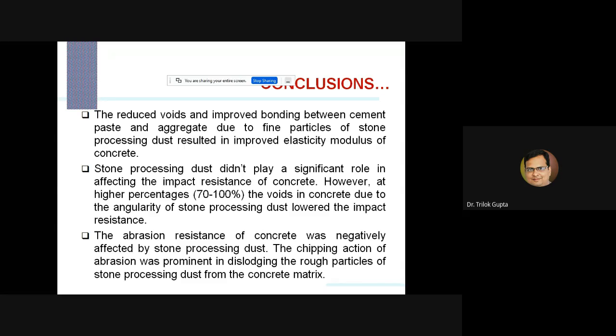However, at a higher percentage, meaning greater than 70%, the voids in concrete due to the angularity of stone processing dust lowered the impact resistance. The abrasion resistance of concrete was negatively affected by the stone processing dust. The chipping action of abrasion was predominant in dislodging the rough particles of stone processing dust from the concrete matrix.